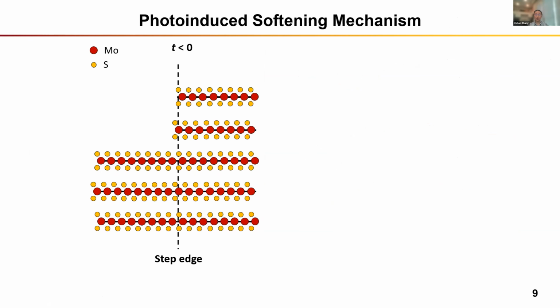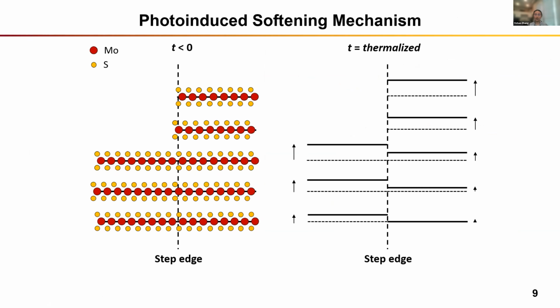Due to the unique structure of the step edge, the photoexcited layer movement is more complicated than the case of uniform thickness. So here I have a cartoon illustration of the structure near the step edge prior to photoexcitation. After the lattice is thermalized, the layers start to move along the z-axis. And due to the different photon absorption profiles across the step edge, the amount of z-axis displacement of each layer across the step edge is different, as noted by the length of the arrows here. So we can see there is clearly a discontinuity at the step edge.